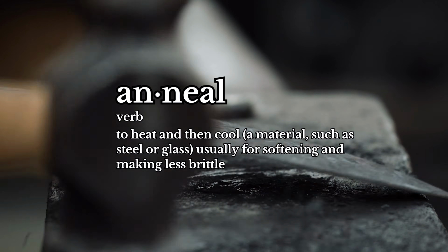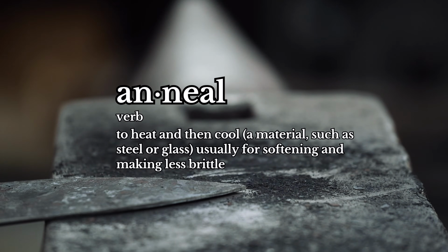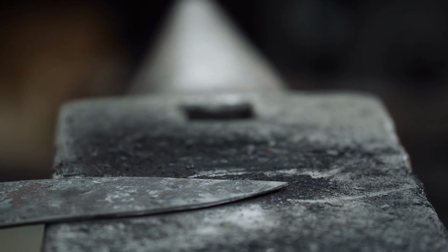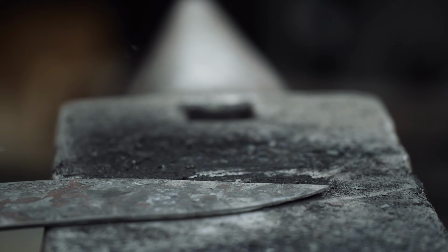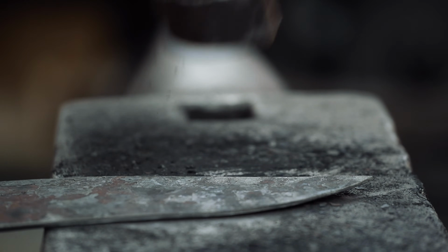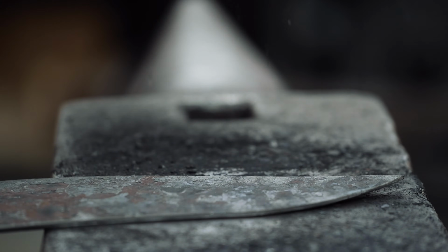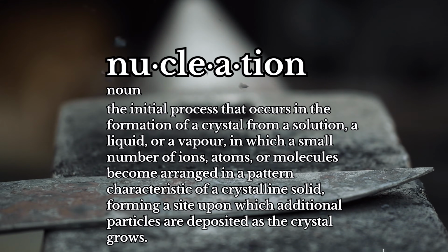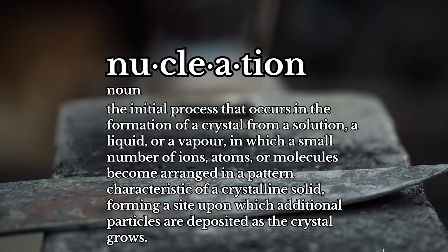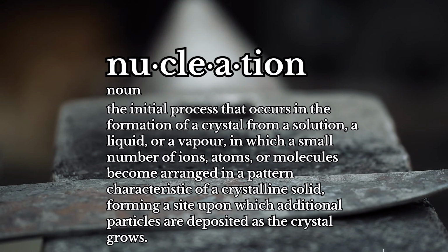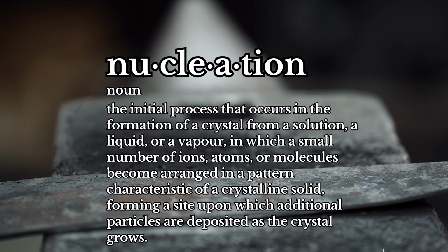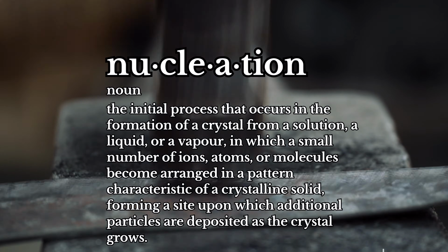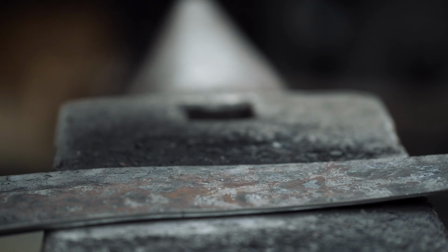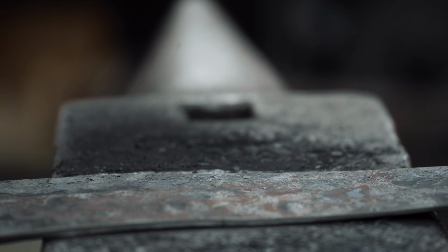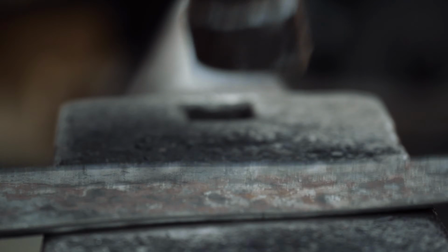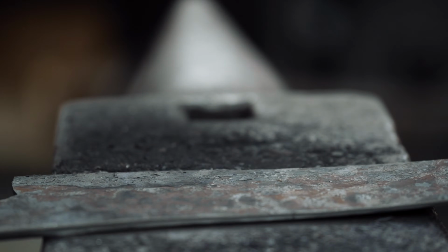If they are a laminate and clad with something soft and malleable, I do some cold forging to, again, compress the cladding, get a better surface texture, and also to create what are called nucleation points in the steel, so that when it's heated up, that carbon goes into solution and is ready for the quench. I've done it without the cold forging before, and I really like the results I get from the cold forging. And on mono steels, I will cold forge too, just much more gently,